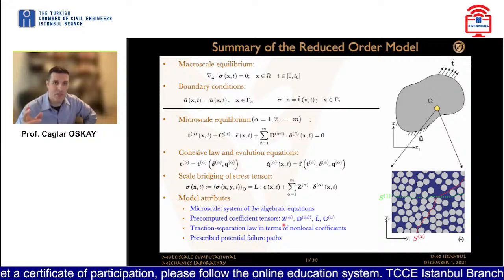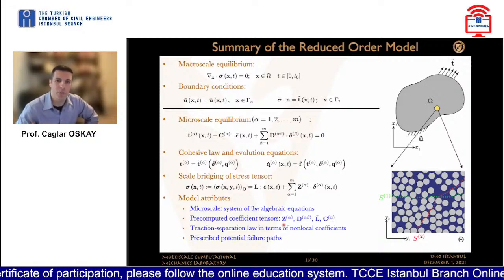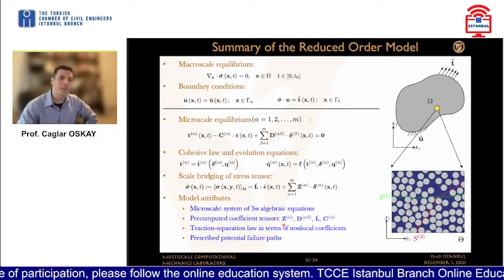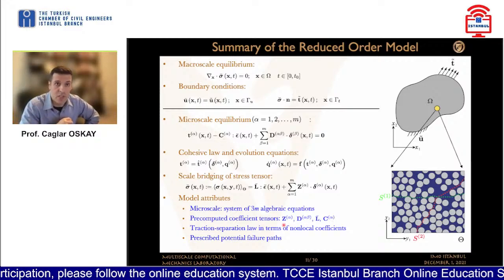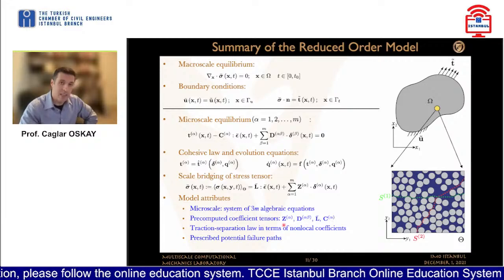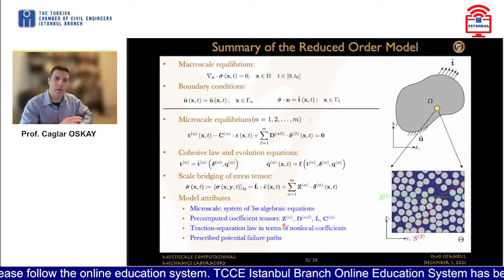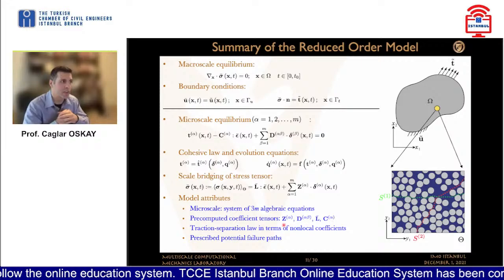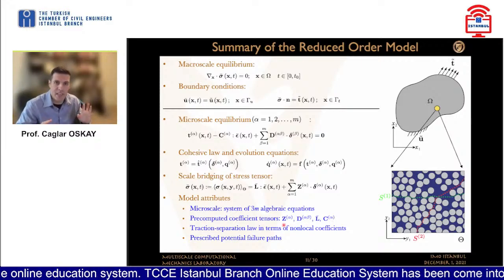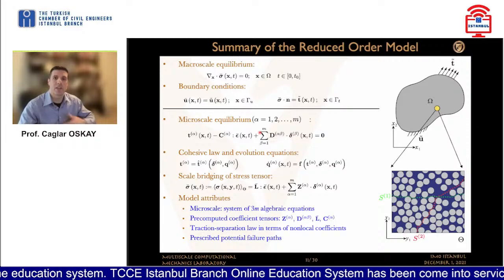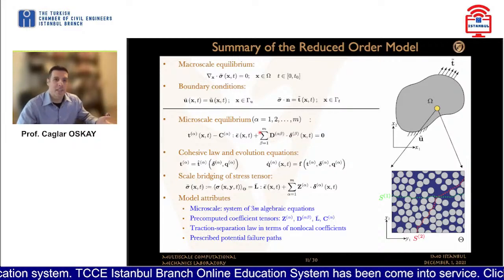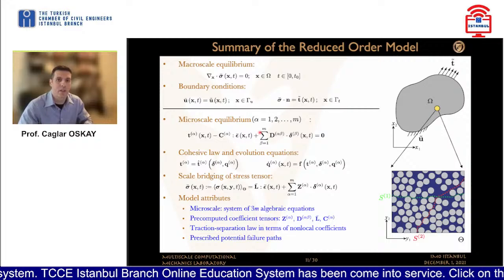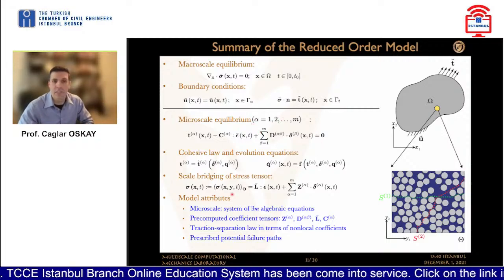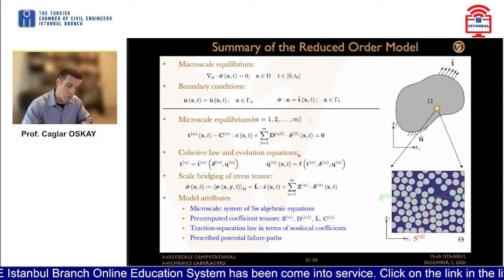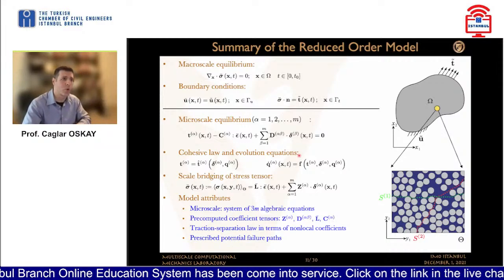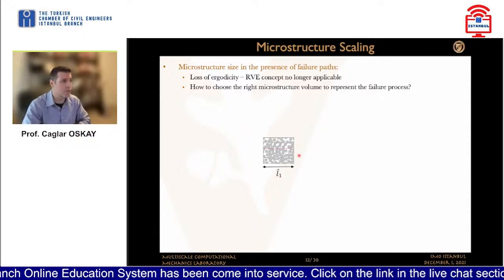These are some tensors, and you can consider them to be constitutive parameters that are computed based on the material microstructural morphology and the crack paths. And they're analyzed a priori. We basically compute those values. After that, it's pretty much a standard finite element analysis, where instead of using a constitutive model such as J2 plasticity model, von Mises plasticity model, we solve this system of equations at the quadrature point. So it's a fairly straightforward system of equations to evaluate.